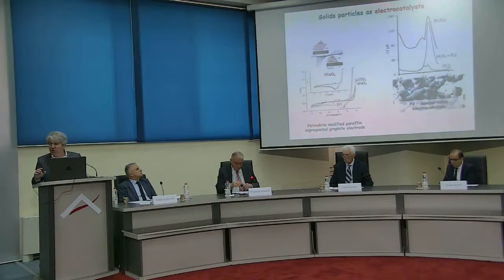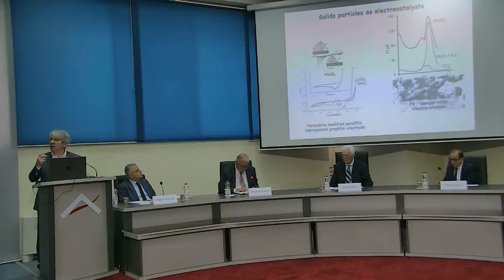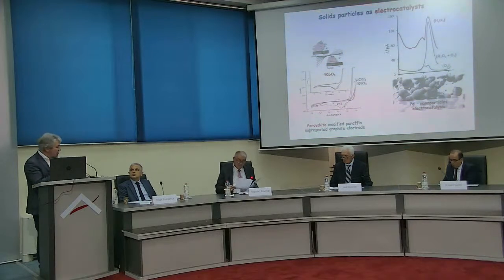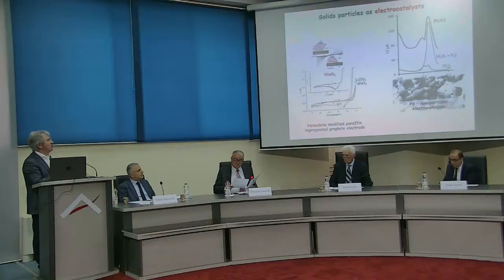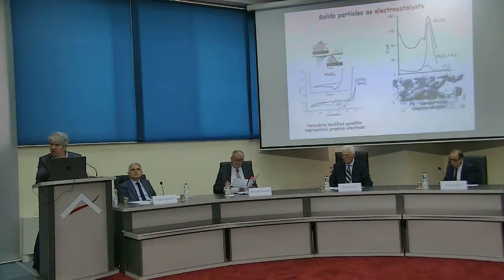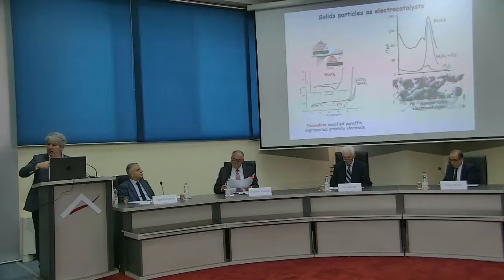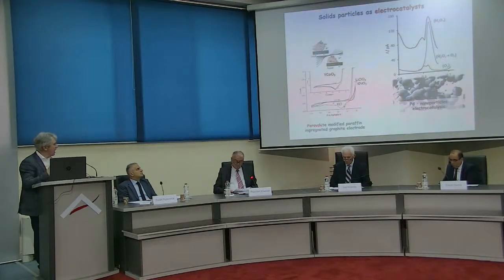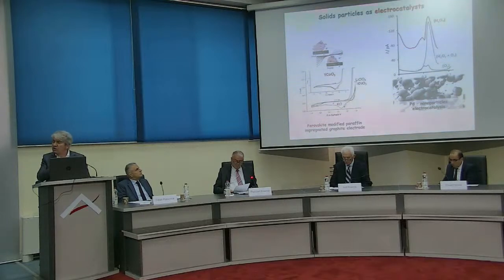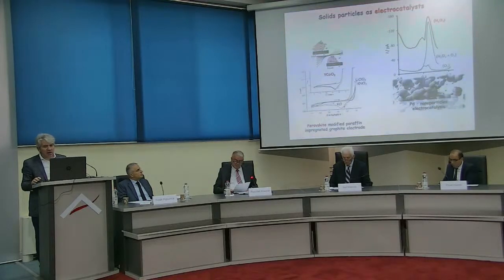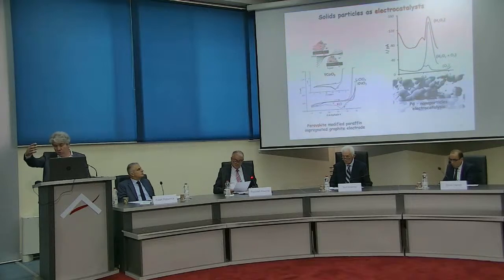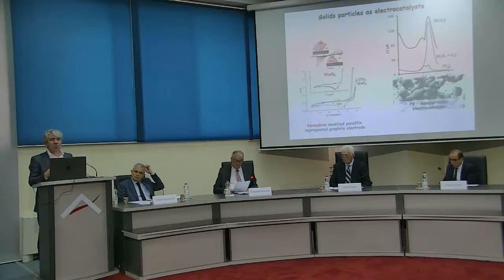In cooperation with the group from Niš for several years, I do cooperate also in this, let us say, classical subject, electrocatalysis with noble metal nanoparticles, for instance, palladium, but now not directly palladium at the electrode, but palladium on graphene or different carbon microstructures and so on. And this is very interesting material for electrocatalysis. Of course, depending on the structure, depending on how big the palladium nanoparticles are, electrocatalysis of very basic processes like oxygen reduction, hydrogen peroxide reduction, and also hydroxide oxidation, which is important for the fuel cell. And that mechanistic analysis has also been done, which is, of course, later important generally for energy producing systems.